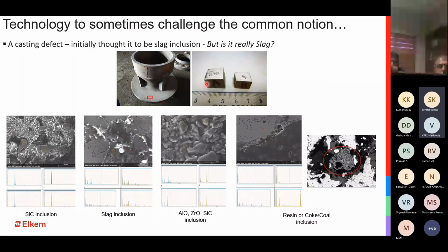the route. And then, interestingly, we also found some resin and coal and coke inclusion inside the casting. So it was a combination of these 4 different inclusions which was giving them the casting defect. So do you think with this kind of a setup, just having a control on slag would have resolved the problem? No. So this is just to reiterate the fact that when we use technology, when we don't go just by the traditional or the original ways of looking into a defect, we will be able to do a much better root cause analysis and eventually get a much better solution to the problem.